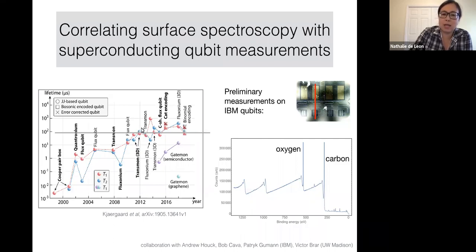Improvements since then have involved looking at the lifetime of a microwave excitation in a very large cavity, but the actual qubit coherence time has been stuck around this level for quite a long time. So what we asked was whether we could learn anything about the surface and then use that for systematic improvements. We had preliminary measurements on state-of-the-art IBM qubits that we had gotten in collaboration with Pat Gumann at IBM as part of an NSF team that we're on. And we just did some preliminary X-ray photoelectron spectroscopy.